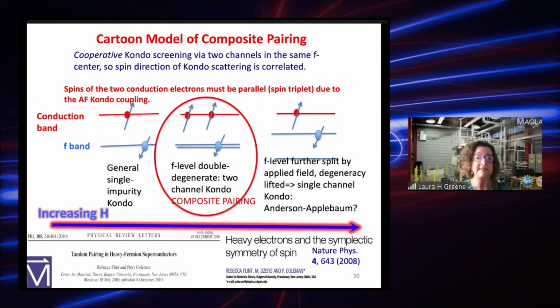The idea is that you have a general single impurity Kondo scattering. Here's an electron scattering. And if you have like a Kramers doublet down at the f level, then you'll have to talk to Rebecca Flint and Piers Coleman for the real details, because I can't really get there from here. But now, because you have your doublet, two separate electrons can Kondo scatter on the single f level. And then you have this two-channel Kondo model.